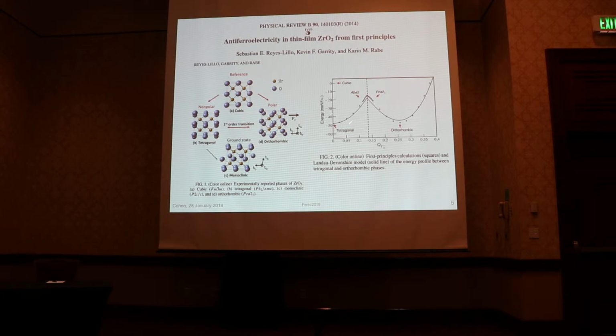But like this work that Karen showed, the energetics are very subtle, so the difference between this polar orthorhombic phase and this nonpolar tetragonal phase is extremely small. So this is the interesting thing. It's true also in the perovskites that the most useful and interesting systems are the hardest ones to do computation, and maybe experiments, for as well, because they're so sensitive, and the whole reason they're useful is because they're so sensitive. But that means it's also a challenge for us as theorists, and as experimentalists, to figure out the details of what's going on so that we can control it. Because I would say right now, the situation is that things are not completely reproducible.